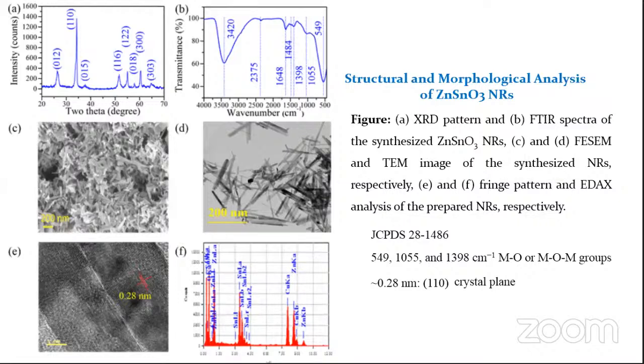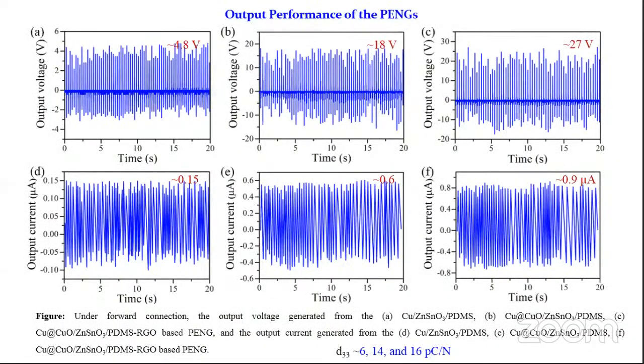Figure F represents the EDAX pattern of the zinc stannate nanorod, which clearly reveals that the nanoparticles contain zinc, tin, and oxygen atoms. After fabricating the PENG, we have got the output voltage from different devices. Figure A represents the device without the copper oxide layer, figure B represents the device with the copper oxide layer but no RGO, and figure C represents the device with copper oxide as well as RGO. From figure A to B, we can see that after inclusion of the copper oxide layer, it gives an enhanced output voltage.